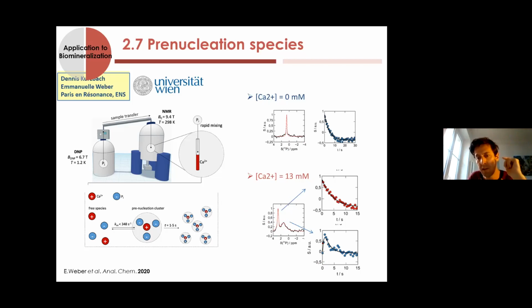Then you see the increase of the signal, meaning you increase the amount of prenucleation species, and then you have the decrease of the species. There are two phenomena: the first is aggregation, because it becomes bigger and bigger and then you precipitate your phase. The other is the relaxation of the magnetization, but that's not the problem.